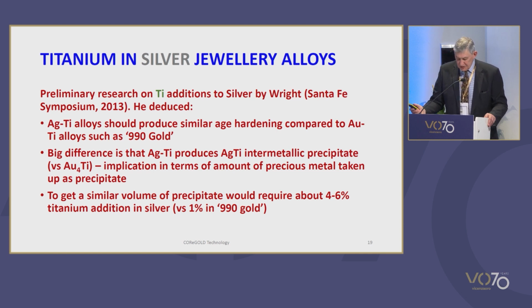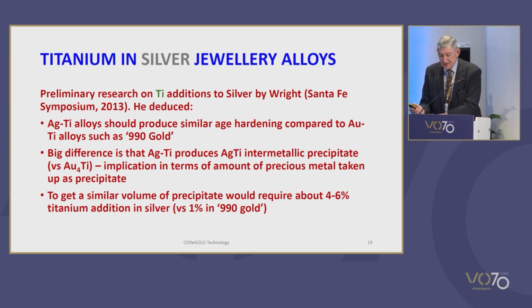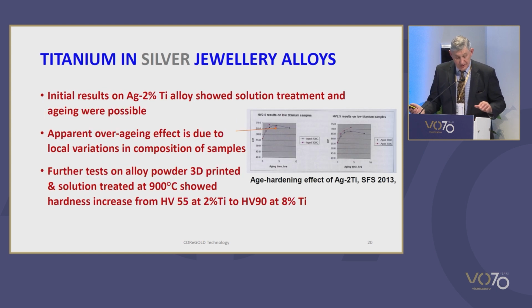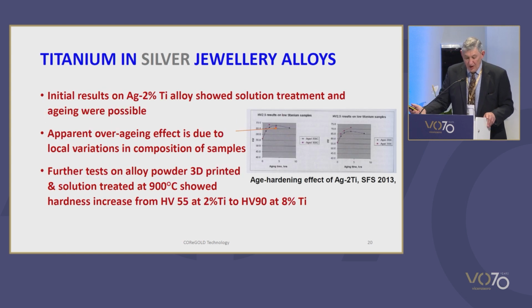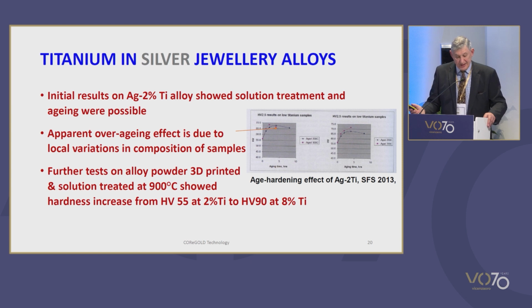A further point was that the density difference between silver and titanium is about half that of gold and titanium. Thus, to get a similar volume of precipitate in silver would require about 4 to 6% titanium compared to the 1% we saw in the 990 gold alloy. Some initial tests on wire made in a silver 2% titanium alloy from a casting sprue indicated that solution treatment and age hardening were possible.